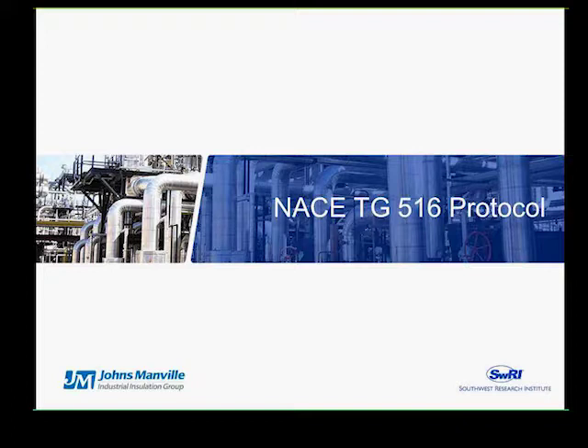Next, I'm going to address the NACE TG516 test protocol for CUI evaluation. The design of the test method is based on an approach that simulates CUI field conditions under any type of insulation material and coating type. Another great benefit of this test method is that it allows for real-time electrochemical measurements that determine the corrosion rate of the metal, as well as the onset of coating degradation. This is very important in assessing the performance-based conditions of a system under evaluation. The test duration is typically set to 26 weeks or until coating failures occur, whichever comes first. Test assembly.